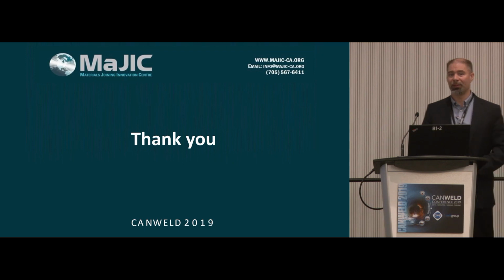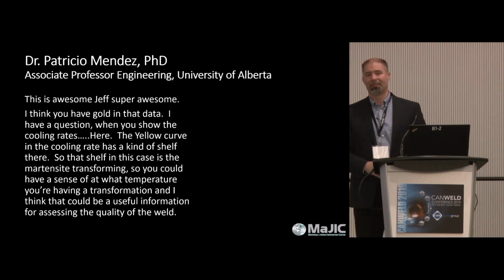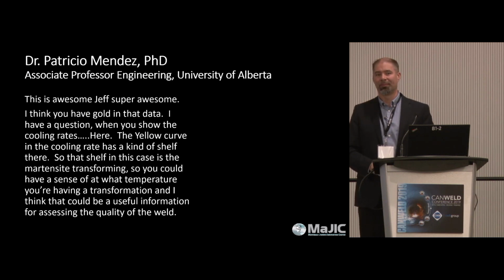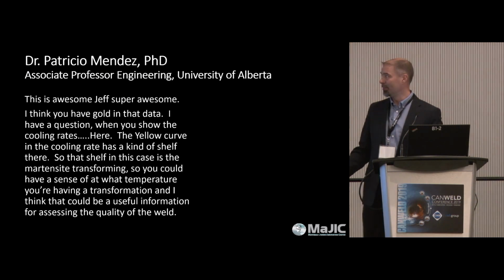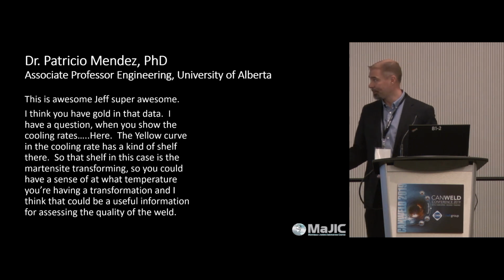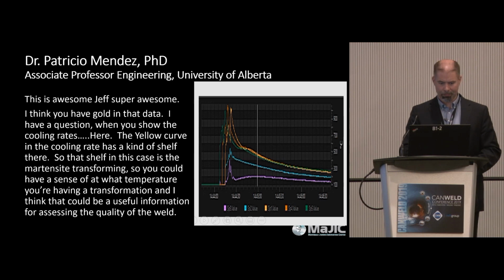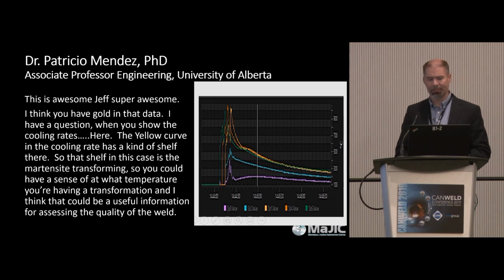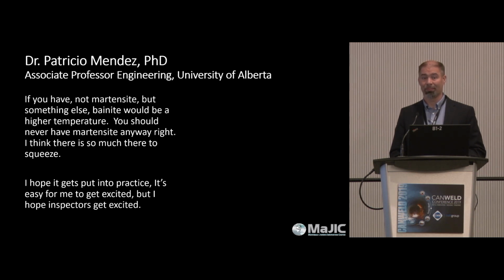Questions? Patricio. This is awesome, Jeff. Super awesome. I think you have gold in that data you have here. I have a question. When you show the cooling rates, halfway here, in the yellow curve in the cooling rate, you see it has like a shelf there. That shelf in this case is the martensite transforming, right? So you could have a sense of at what temperature you're having the transformation, and I think that could be useful information for assessing quality of the weld. For example, if you have not martensite but something else, bainite, would be a higher temperature. You should never have martensite anyway, right?